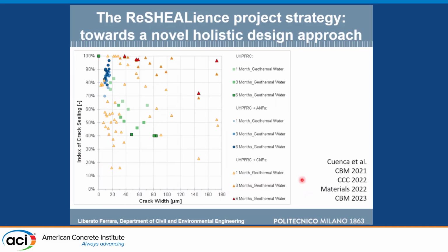And see here the results of the crack sealing, because we expected the cracks as they were going to close. For the mix with alumina nanofibers as compared to the reference, which is the green, you see we always have a better capacity, and we always have very, very narrow cracks. And also with nanocellulose, we were able to keep the cracks very narrowly open and have an improved self-filling capacity.